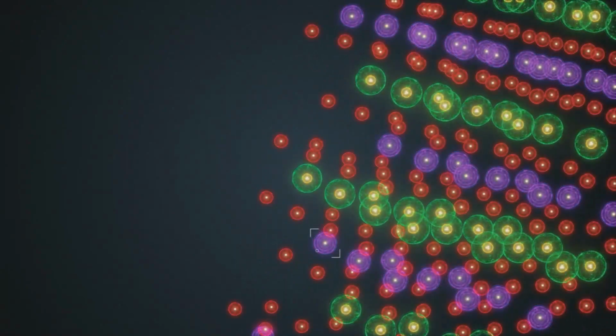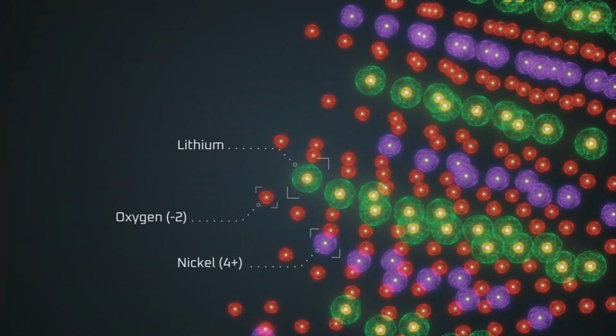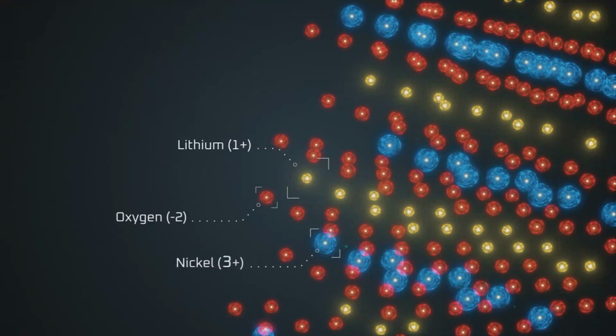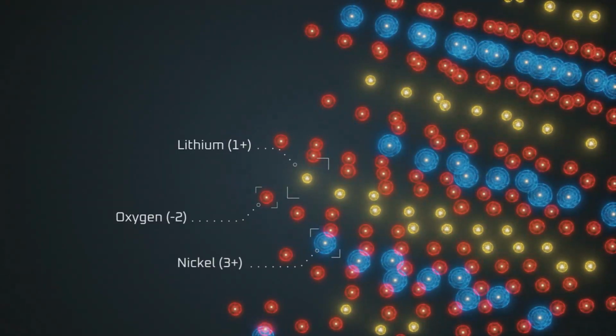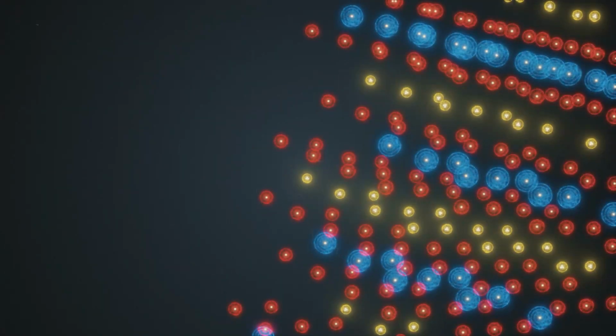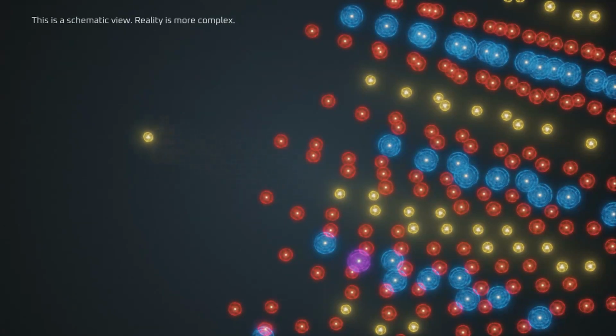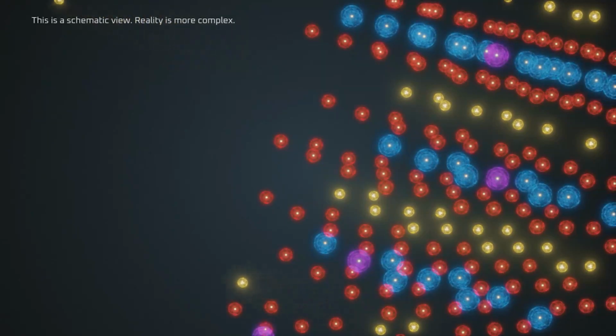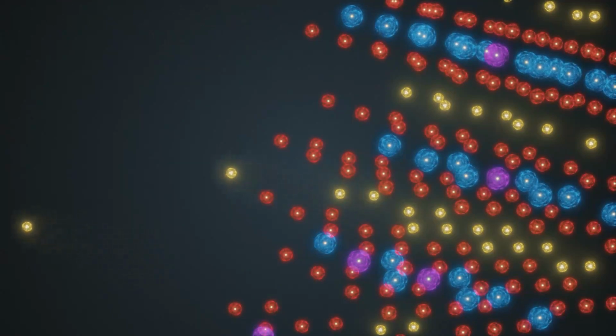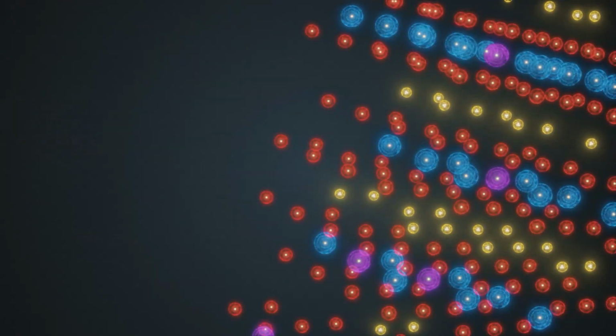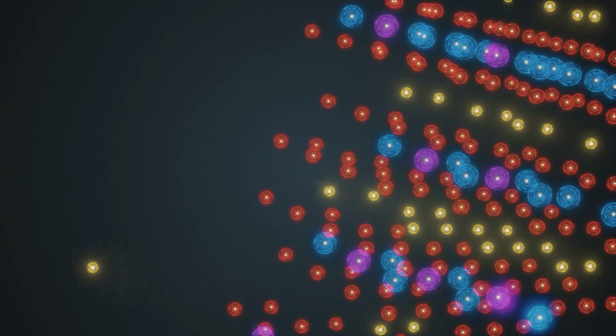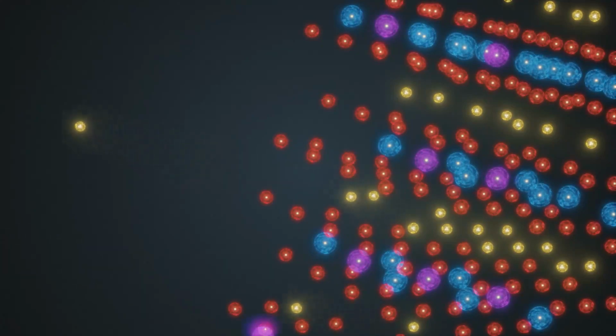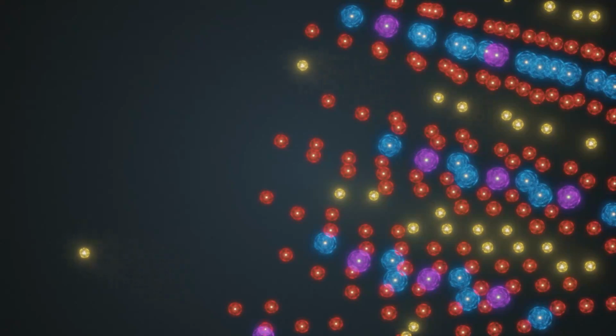In lithium nickel oxide, the nickel and oxygen are strongly bonded to each other and borrow an electron from lithium. This is because nickel oxide has a strong potential to borrow electrons, and lithium has electrons readily available. When the battery is connected to a charger, lithium ions are liberated from the lithium nickel oxide crystal structure to the electrolyte solution. At the same moment that the ions are liberated, electrons are liberated from the cathode and conduct to the anode. However, overall, the nickel oxide material has become more electronegative, which means it's seeking to borrow electrons now that electrons have been stripped away.